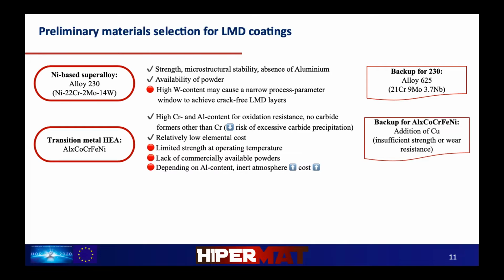Second is transition metal high entropy alloy. This has been selected on the basis of its high oxidation resistance, it tends to form fewer carbides, and also has relatively low elemental cost. It is also important to consider the technical as well as business risk in this. The lack of commercial powders can be a drawback for developing such high entropy alloys. Therefore, in this case, if there is insufficient strength or wear resistance for the selected high entropy alloy, the backup selected is the addition of copper.